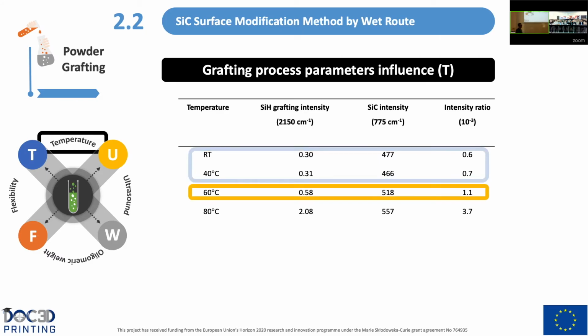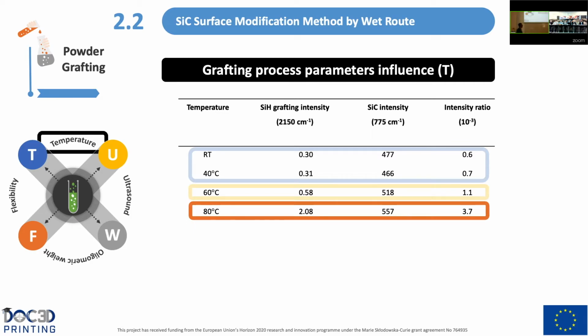By increasing the temperature to 60 degrees, we can start to observe an important increase in intensity ratio. But by increasing to 80 degrees, compared to the other values, we observe a huge increase of the intensity ratio. But why are we not using 80 degrees instead of 60 degrees?